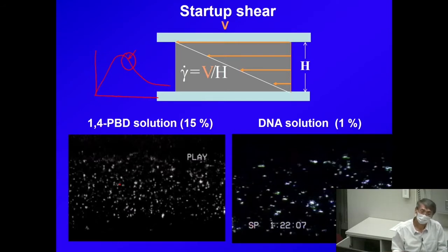Although overshoot is overshoot, and I said overshoot by definition should be called a yield point. It's by definition the termination of elastic response. And how can an elastic response terminate unless you break the elastic structure? So in that sense, in retrospect, this overshoot is utterly trivial in its meaning. But as I said, we were unprepared. We didn't know any of this. Therefore, the movie helped us, if you like. Any question on this point?